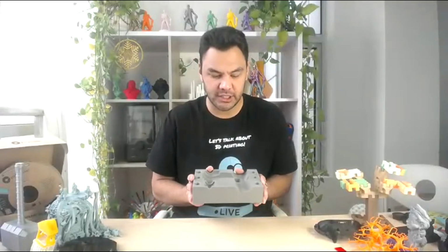Why I mention this is because if you do have experience with other nylon, you may have experienced a lot of warping issue. And usually you solve this by increasing your bed temperature or increasing the chamber temperature. However, for our particular nylon, that's the exact opposite. We have formulated a technology that allows you to print your nylon parts without any warping issue. However, if you increase the bed temperature or the chamber temperature, then you will start to have warping issue. The simple explanation is we are playing with the crystallization behavior of the material in order to control the warping. So we control the internal stress accumulation within the layers, which will control the warping.